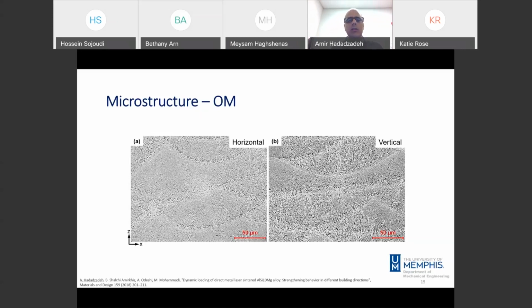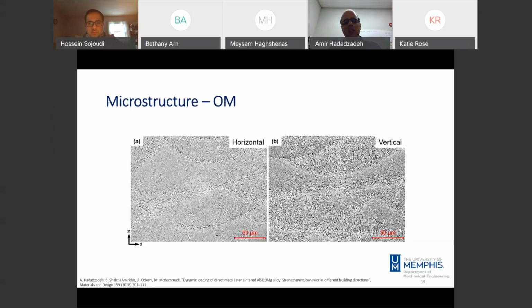And also, there was no major concern regarding their overlap or the interaction between, or if you call it adhesion of different layers. Because during the mechanical test under tensile loading, the properties of the materials were pretty similar for both horizontal and vertical samples. So we didn't observe any evidence of any problems between the layers.